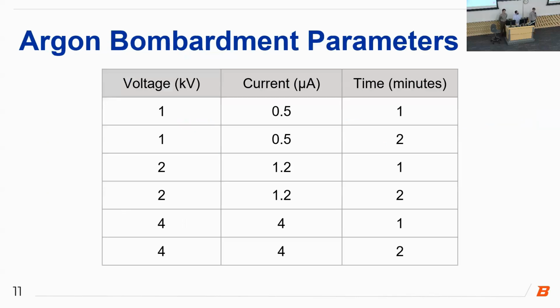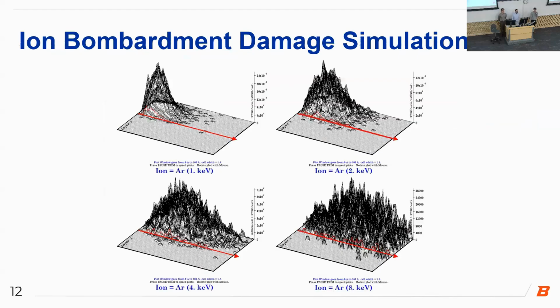So these were our parameters for our argon bombardment. We had 3 accelerating voltages and 2 time levels. And the way that we determined these were through TRIM simulations. So the long axis is 100 nanometers, and we use these simulations to qualitatively assess how deep damage would occur in our samples.